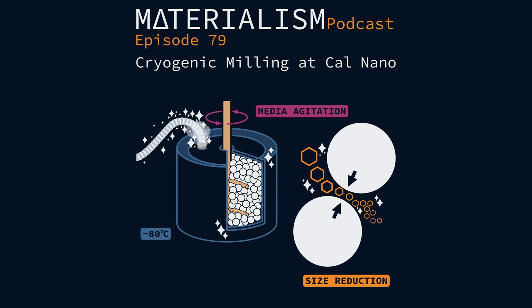Larger particles are going to have more drag, so they're going to stay towards the edge. But once they get small enough, they can escape the vortex and exit out a chute. By controlling those speeds, you can control what powder size actually makes it out. That's cool. So it's a separator and a particle size reduction in one. Yeah, you can get some very narrow, high purity distributions.